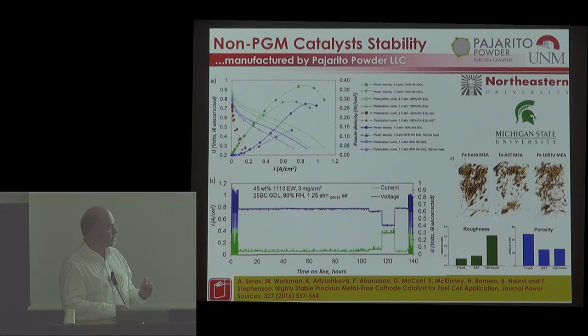First of all, it's a materials instability, a restructuring of the pore sizes, and I think I tried to convince you that the pore size distribution of this catalyst is important for its operation in the membrane electrode assembly. And the second thing that happens, not illustrated here, is the functional degradation of the catalyst, which is related to moving of the line of capillary condensation from the microporous layer into the catalytic layer, which essentially means, in plain English, flooding the catalytic layer.